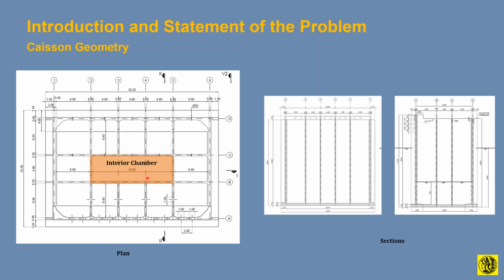here, during slip forming, which lasts about 7 days, there is enough storage area for the reinforcement to be positioned, which has to be continuously erected during slip form, and also for the controls of the hydraulic equipment that manage the slip forming operations. So this chamber here results in a void basically throughout the depth of the caisson, which is remaining in the middle of this cross-section of this plan.